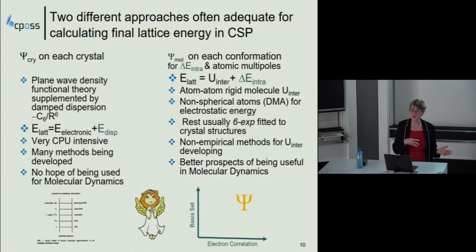Once you're doing conformationally flexible molecules, you have to repeat the calculation for every conformation, and you also have the energy penalty, the difference in the conformational energy that the molecule has gone into a higher energy conformation in the crystal structure in order to improve the intermolecular interactions and so give the lower lattice energy. And we use database technology to cut down the number of repeat calculations. Usually, in addition to the distributed multipoles, we're using empirically fitted explicit repulsion dispersion potentials. But this is an area of research of developing non-empirical methods for all the terms in the potential.